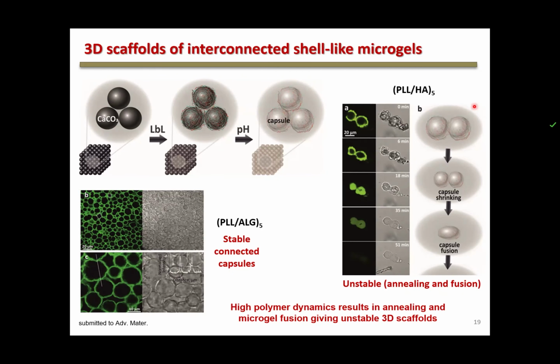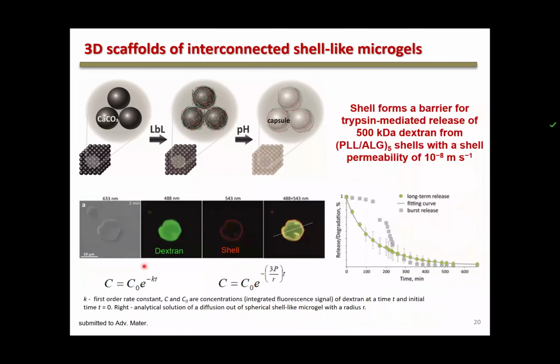And again, for instance, if you take some microgels which show strong shrinkage, like polylysine hyaluronic acid that I've shown you before, they never form stable 3-dimensional structures because they start just to fuse. They are more like fluent polymer network, and they never form a stable structure. So opposite to this, polylysine alginate, little change in the chemistry between alginate and hyaluronic acid, and this is huge in the stability of the structures, giving very nice 3-dimensional structures. So here we basically did pattern 3D, if you want, by changing the size of these calcium carbonate particles. One can also change the pores between these spherical objects as well.